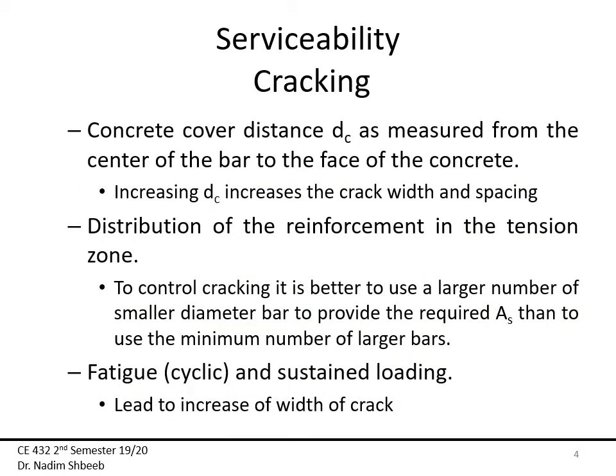Another factor is the concrete cover distance, which is measured from the center of the bar to the face of the concrete. So if this is my lower section, and I have a bar here, then I'm talking about this distance, from the center to the face, and this will be my dc. Again, increasing this distance will increase the width and the spacing of the cracks.